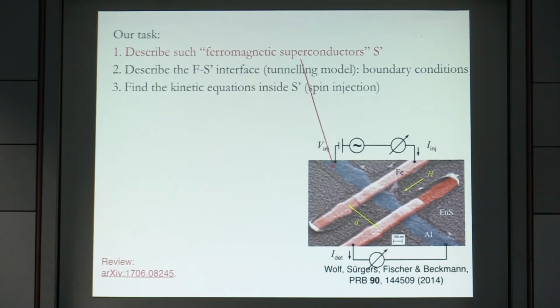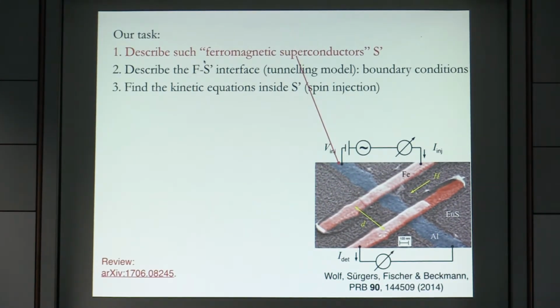So we set up a theory for this experiment, and in retrospect we can tell that we divided our task into three parts. First, we need to understand such a ferromagnetic superconductor, for example, what happens in this case where you have the superconductor on top of the ferromagnetic insulator. Then we need to describe what happens exactly at the interface between this injecting ferromagnet and the superconductor, or the ferromagnetic superconductor, which is basically giving just boundary conditions for our kinetic model. And then the third task is to find the kinetic equations inside the superconductor. It turns out that once we did this, we found some new interesting results, which I'm about to tell you.